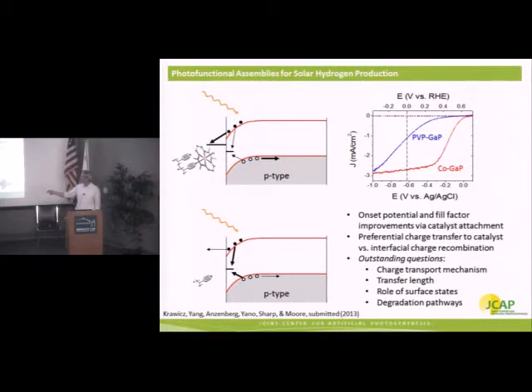When there's no catalyst on the surface, this process actually begins to dominate because you need to apply larger and larger potentials in order to separate this charge, prevent this reaction from occurring, and get to the overpotential required to drive the hydrogen evolution reaction. For the case of a semiconductor where we have the catalyst on the surface, such as in this red case, charge transfer is promoted to the catalyst, which means the recombination currents, the loss of efficiency, is reduced. And so we have an improvement of the overall performance of the photoelectrode by integration with catalyst.